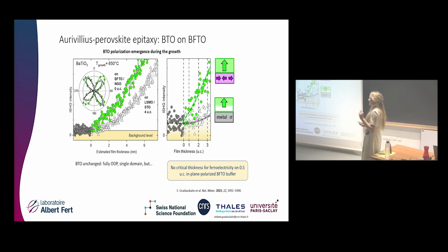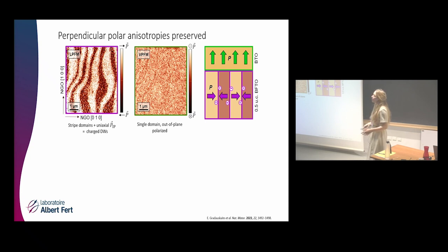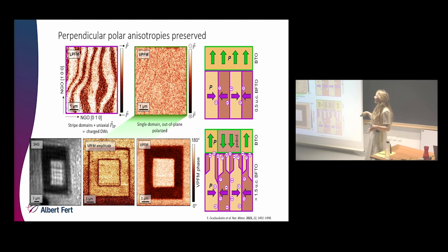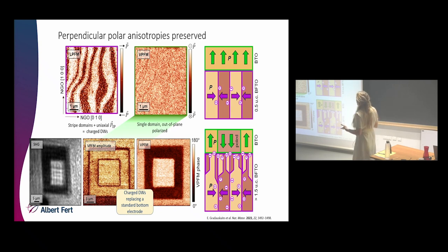we can indeed have no critical thickness for ferroelectricity on even as thin as half a unit cell in-plane polarized BFTO buffer. And then we went ahead and did some piezoresponse force microscopy. So we could identify the stripe domains laterally in this layer and single domain in the BTO layer. We could even switch it reversibly without any electrode, because mostly we know that when the films are thicker, they have these stripe domains, so there will be these carriers everywhere that can come and help to enable the switching. So in fact, it shows that even without an electrode, by just using charged domain walls in the bottom ferroelectric, we can replace what we usually need for switching. So we can replace a standard bottom electrode with that.